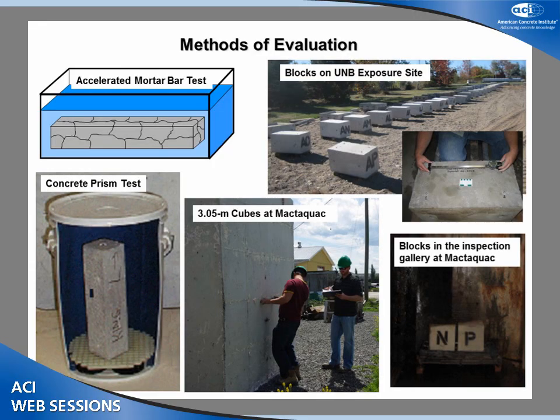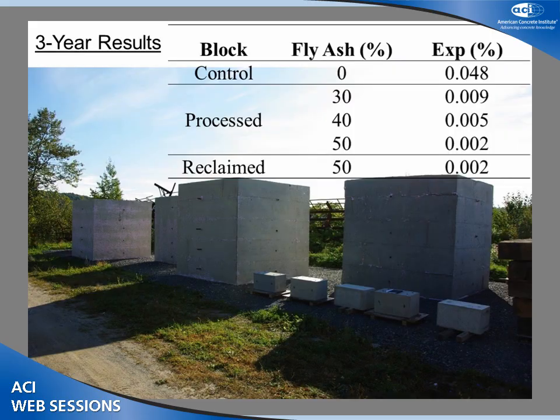And Mike did work on the mortar bar test and the concrete prism testing. They got smaller exposure blocks outside, and they got these big 10-foot blocks out there, which were cast. So they'll almost have 20 years on the blocks by the time they need to pick the aggregate. That shows the blocks outside, and it shows the expansion after 3 years.